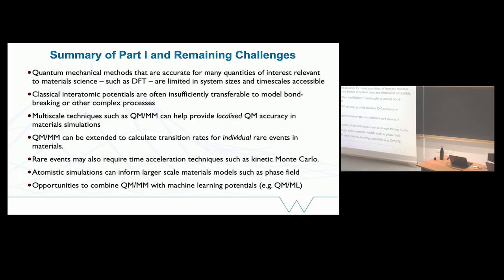So we can just literally stitch together a combined vector of forces where we have quantum forces on quantum atoms, classical forces on classical atoms. We do one slight refinement to make sure we conserve momentum, which is to ensure that the forces sum to 0. So you can take the total force divided by the number of atoms and subtract it. That's a small correction, and then you have Newton's third law back again. But you don't have energy conservation because those forces are not the derivative of anything. But that's really it. So the way in which the padding is done ensures that every force that you are using is an accurate force, and then you don't need any other interface terms.